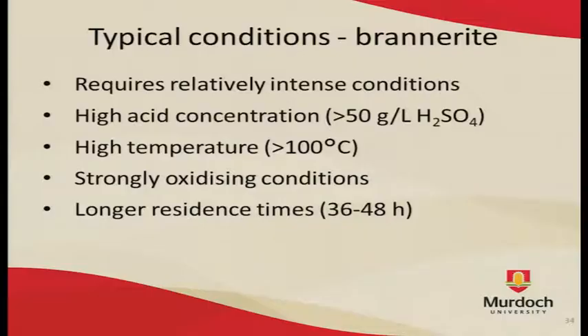So I was not able to find too many industrial examples, but under typical leaching conditions, brannerite will dissolve quite slowly, if it does at all. So for this reason, relatively intense conditions are needed. I say relatively intense rather than intense because these sort of conditions may be normal or even mild compared with the leaching of some other commodities. So higher concentrations of acid are used, typically upwards of 50 grams per litre sulfuric acid, which corresponds roughly to a pH of 0.3 and below.